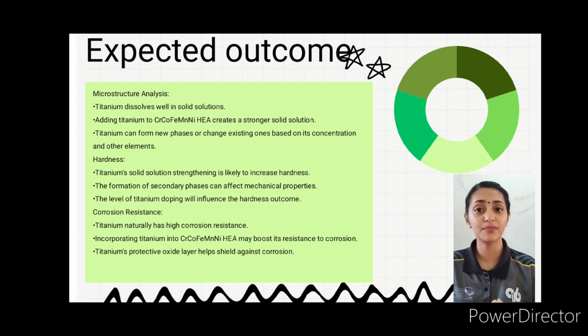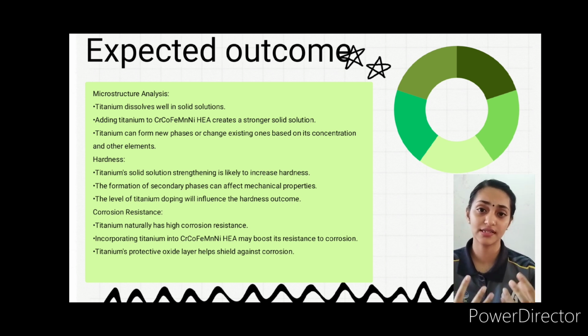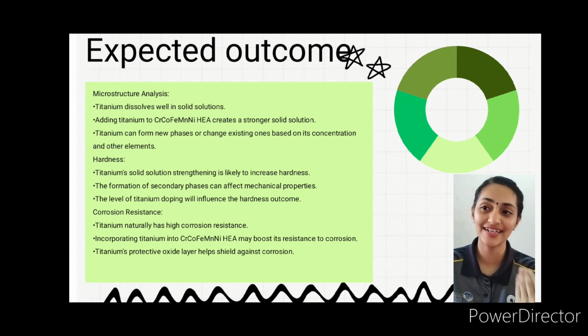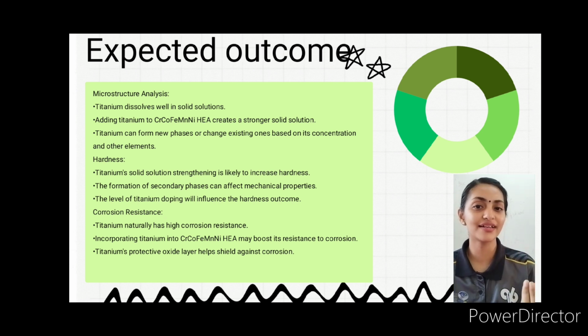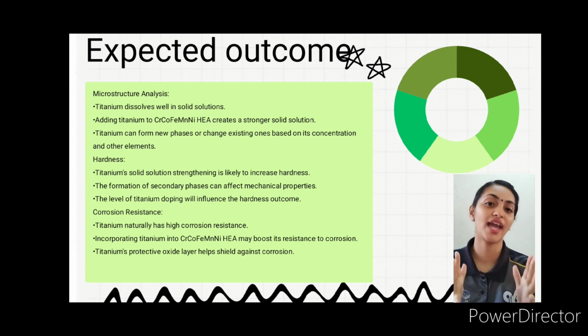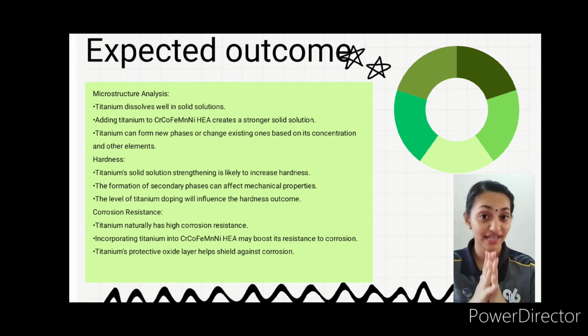My expected result for this research is, first of all, for the microstructure analysis, I expect that when we add titanium to the Cantor alloy, it will dissolve well in solid solution and create stronger solid solutions. Titanium can also form new phases, which can cause changes in the lattice parameter spacing, and it will also cause distortion, which helps to enhance the hardness. Next, for the hardness, I expect that adding titanium will increase the hardness and enhance the mechanical properties by forming a secondary phase in the high entropy alloy. And finally, for the corrosion resistance, I expect that doping with titanium can improve the corrosion resistance by forming a passive layer on the HEA, since titanium naturally has high corrosion resistance.